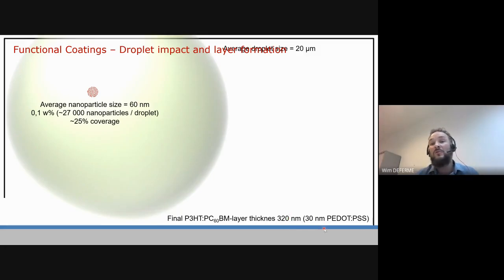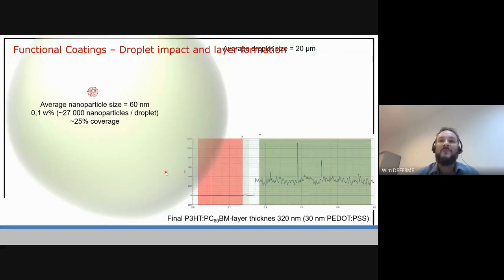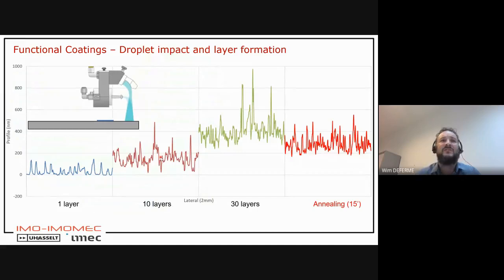So if you want to go to 30 nanometers with nanoparticles, you really have to go to very small nanoparticles. And with polymers, of course, a very low concentration of your functional material. This is a final result, a topographic image where you see the roughness still, because these are nanoparticles. You still see quite some roughness on the final layer. So then you also need post-processing to smoothen these layers out. This is a view of this post-processing.